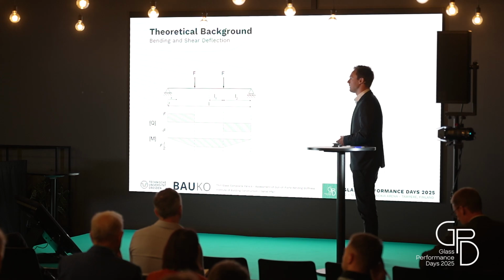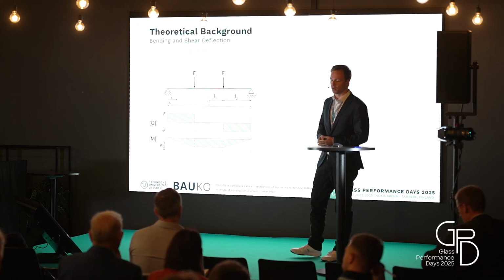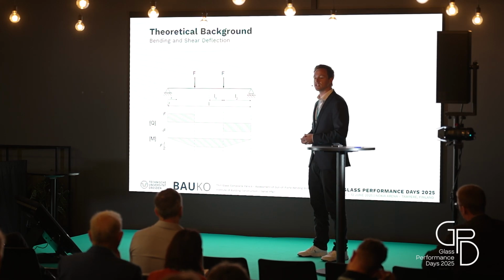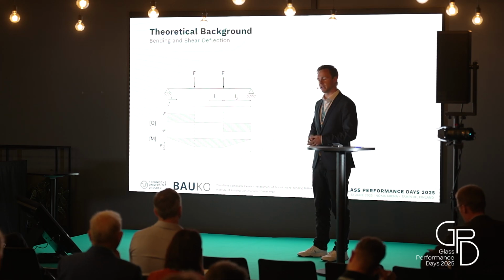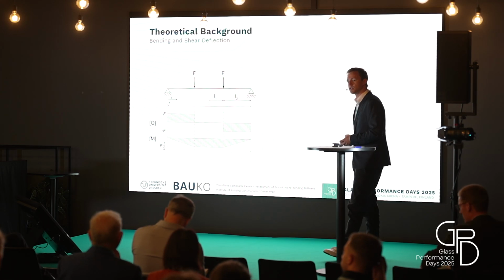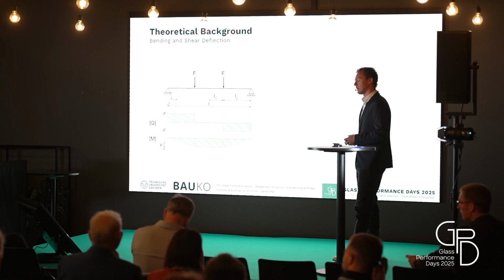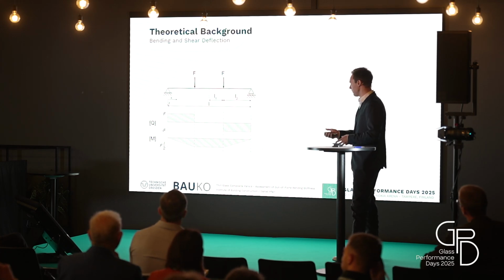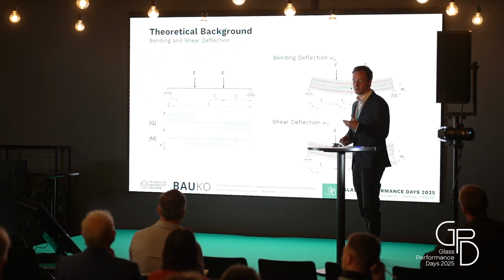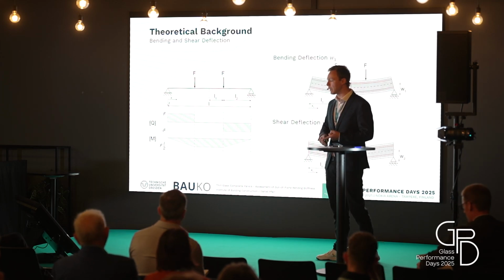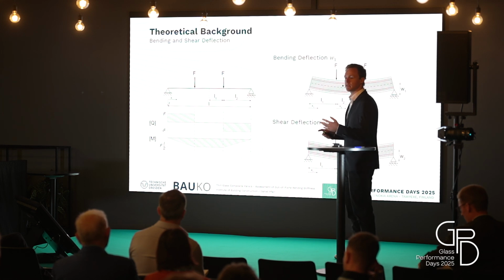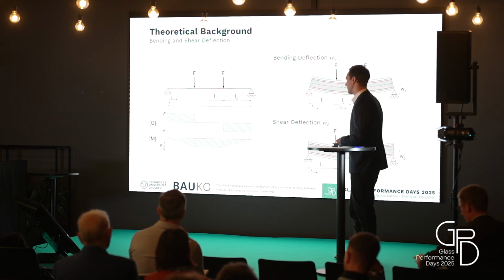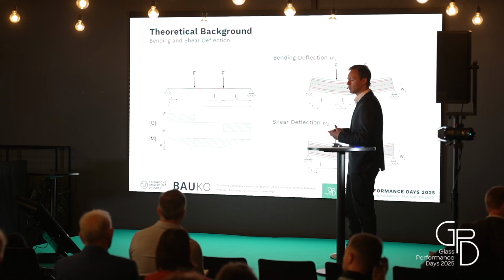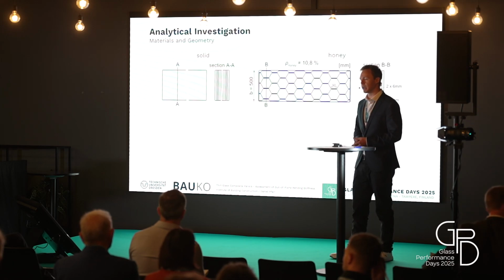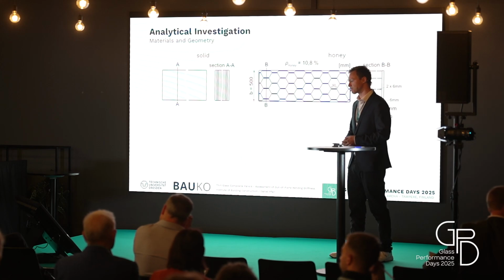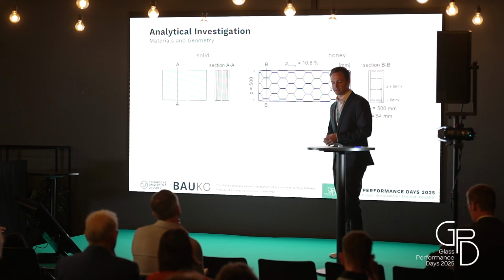So with that stiffness calculation, we can go one step further to the calculation of the bending deflection and the shear deflection. So that is our basic setup, which we are replicating later on in the experimental investigation. It is a 4-point bending setup, and now it's quite important to differentiate between the bending deflection and the shear deflection, representing the two stiffnesses we have calculated before. These both add up to a total deflection, and that is something we can then compare with our experimental results.